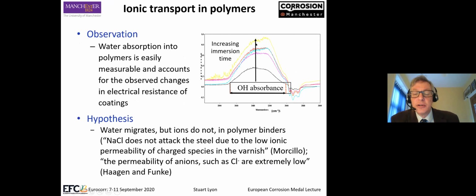One of the ways we can look at water absorption is by infrared absorbance. This is the IR absorbance band. The area under that curve is quantitative to water uptake, so we can determine the amount of water present in the coating by reference back to a standard. So the hypothesis we have is that water migrates, but ions do not migrate in polymer binders. Lots of people have said this: sodium chloride does not attack the steel due to its low ionic permeability, and the permeability of anions such as chloride is extremely low. I have to say, thinking about it, if those things are true, then things like polymer desalination membranes can't possibly work. But hey, we'll do the experiment and find out.